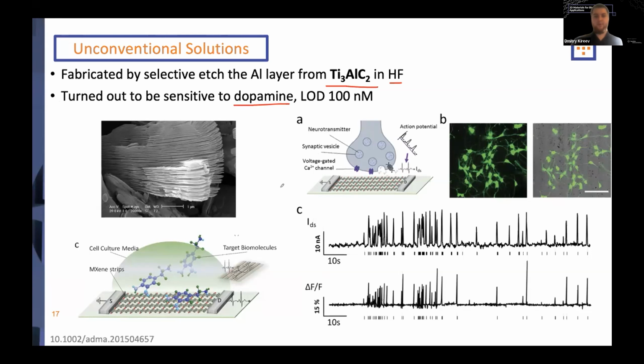And dopamine is a really important molecule that, besides being the one that makes you happy, is also a vehicle that goes between axon and neuron when the communication happens. So it turns out that this 2D material is sensitive to dopamine, which was confirmed by electrical recording and optical recording, when the dopamine sensing happens and when the fluorescent recording of the electrical potential firing is happening.